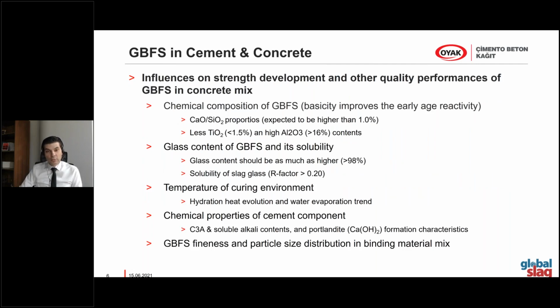I want to give some quick details about the concrete mix and its effects, what we look for according to our experience. The basicity of the product is critical, especially for early age reactivity. Titanium oxide and aluminum contents are important figures for chemical reactivity. Glass content is critical; it is related to the granulating stage, and its solubility is also important. When adding GBFS in cement and concrete, the curing environment matters because its hydration heat evolution and water evaporation trend are critical. It is one of the advantages of GBFS, but on the other side, it should be controlled well.